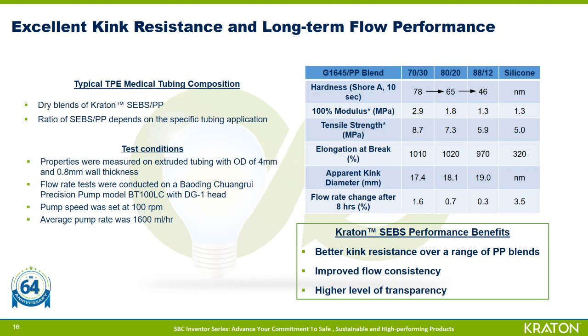Here we present an example of Kraton SEBS and polypropylene blends in medical tubing application. The ratio of SEBS to polypropylene really depends on the hardness requirement of the final tubing, and it can vary from 70-30, for example, in an IV tubing application, to about 80-20 or 88-12, for instance, in a peristaltic pump application.